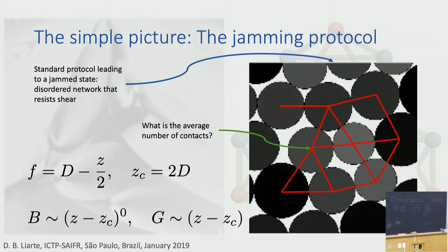And in the jamming transition, you can think of a phase transition where the connectivity jumps from 0 to some value for the bulk modulus. So there is a first order phase transition for the bulk modulus, and it grows continuously as you increase the connectivity for the shear modulus. So this is a typical example of a jamming transition.